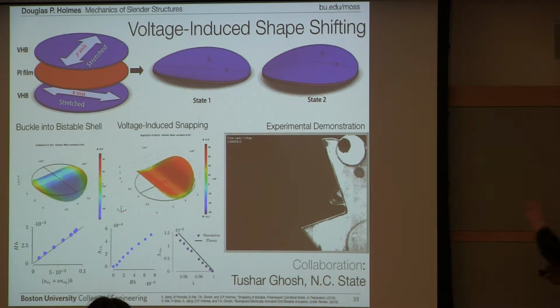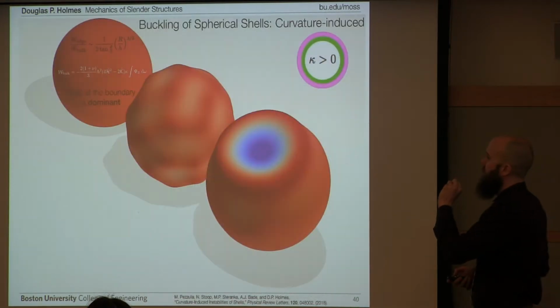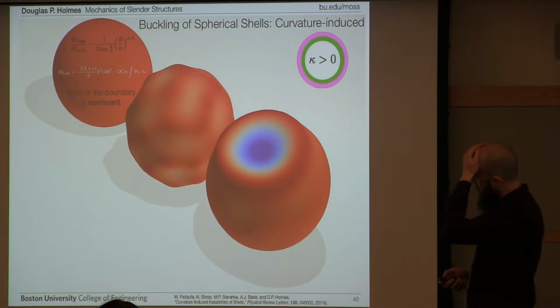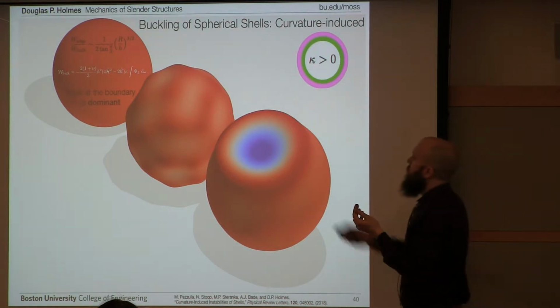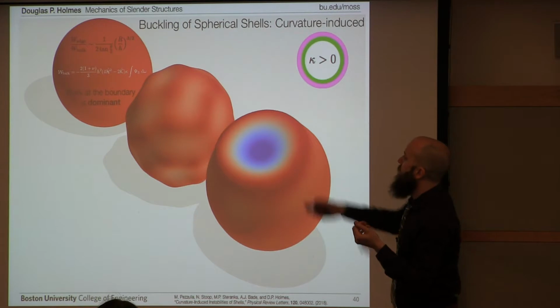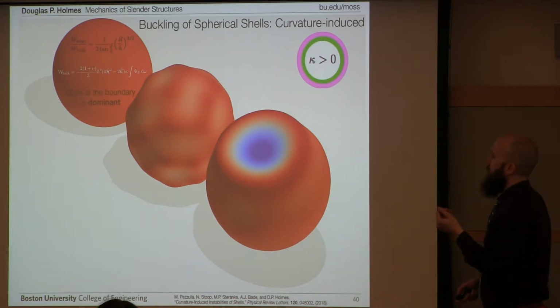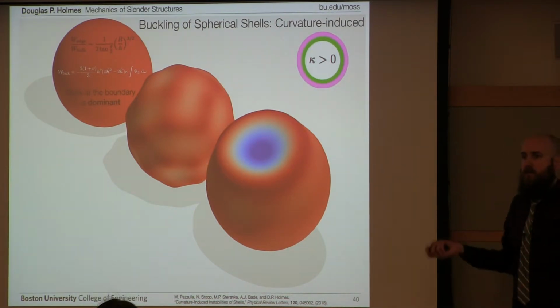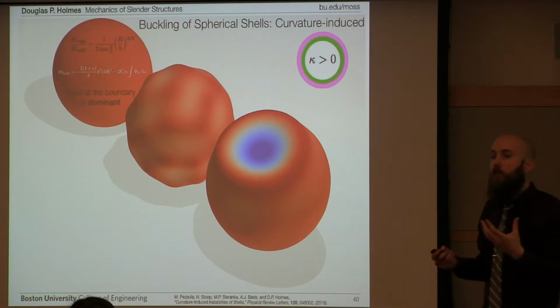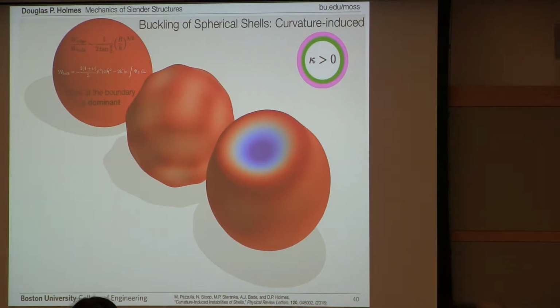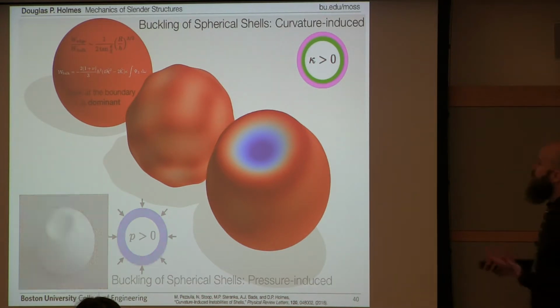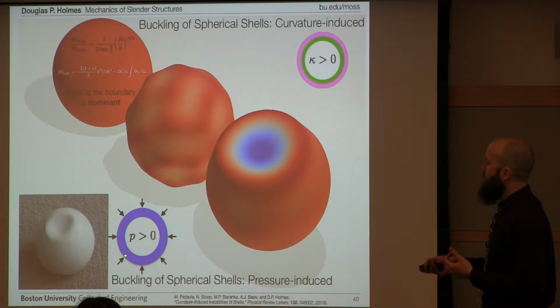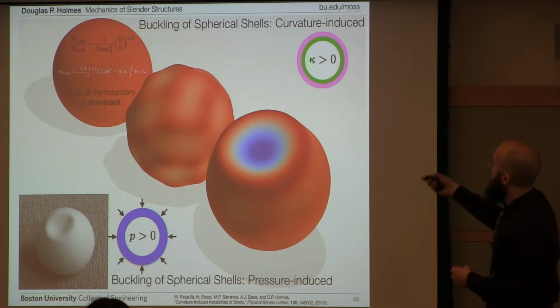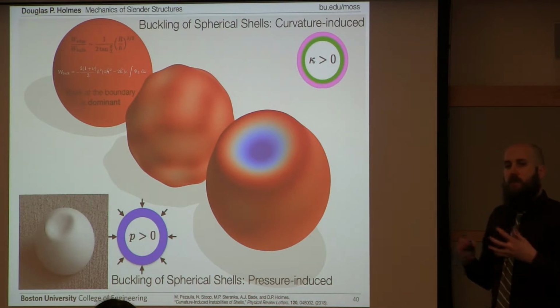So this is what happens when your shell is open. What happens when your shell is closed? Well, we talked about how the edge work is completely dominant over the bulk work. But if there's no edge, then that doesn't matter at all. And all you're left with is that bulk term. This is analogous now to the pressure buckling of a spherical shell. You apply a positive pressure to the outside, this shell buckles. You apply a positive natural curvature, this shell buckles.